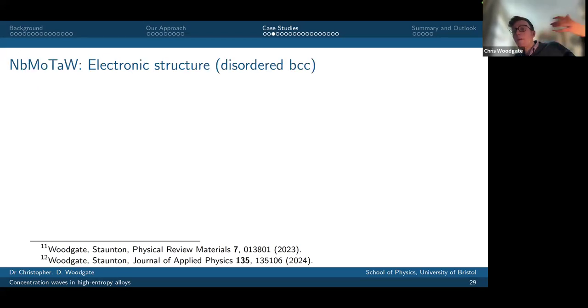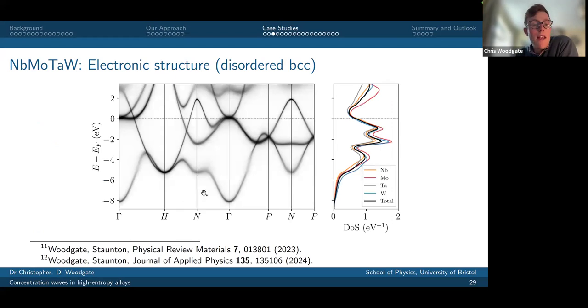So I start by doing my KKR-CPA calculation. Here I'm looking at the Bloch spectral function, like the band structure, but for the disordered alloy, and the electronic density of states. The first feature I want to highlight is that all of these elements are pretty chemically similar. If I look at the species resolved density of states, all of the curves lie pretty close to the average density of states, this black line that I'm plotting here. But what you find is that niobium and tantalum have a reduced valence compared to molybdenum and tungsten, and that means that their species resolved curve sits slightly below the total density of states curve, because they have just one fewer valence electron associated with them, and that'll be important in a second.